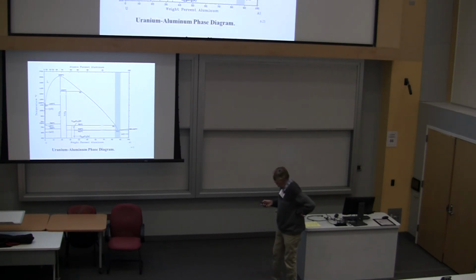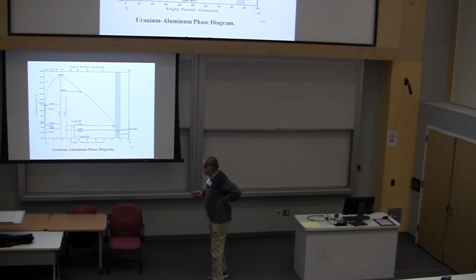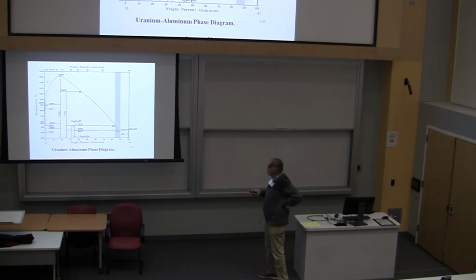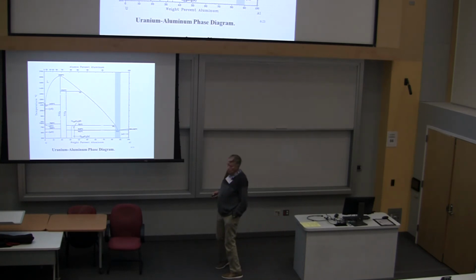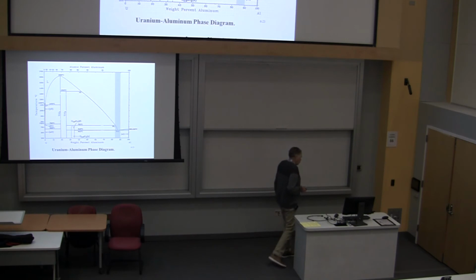And then there's this other heavy fermion superconductor that we worked with, which was uranium beryllium-13. So the question was, can we grow it? You can see here, you can get a lot of uranium into molten aluminum. I mean, you can go out 10-15%, and typically you're running at, of order, 5% of what you want to grow out of these phase diagrams. And there are no compounds between aluminum and beryllium.